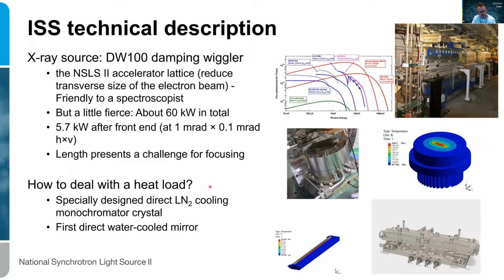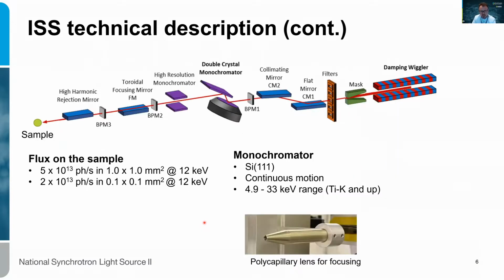So we had to deal with this in the design stage by a special direct liquid nitrogen cooled monochromator and a water-cooled mirror, the first optical element. And it seems to be working quite well. We get resolution that's not affected by thermal distortions of the different optical elements, pretty much in line with the spectral resolution characteristics of the bending magnet equivalent.